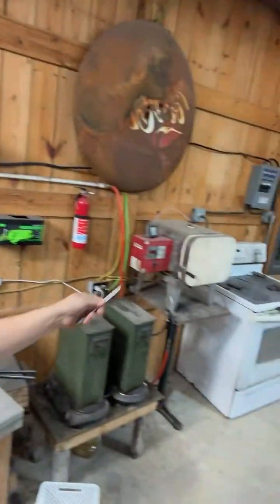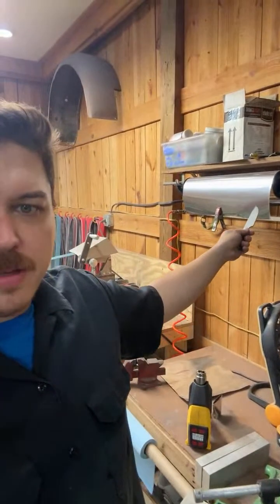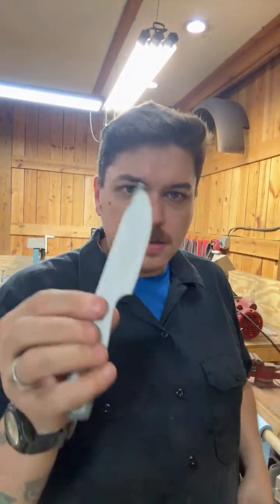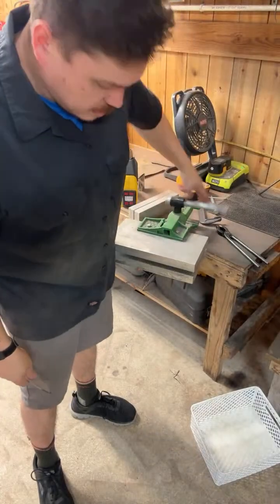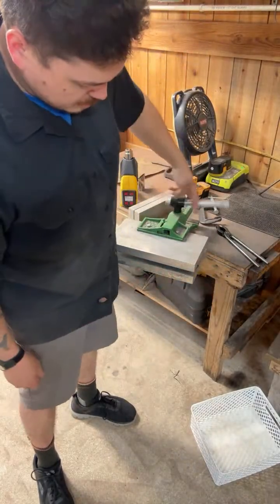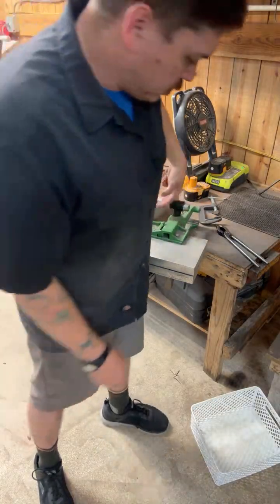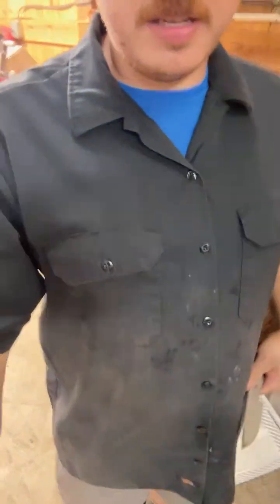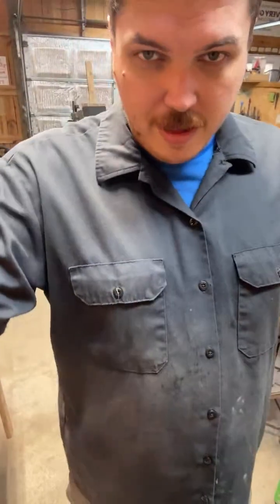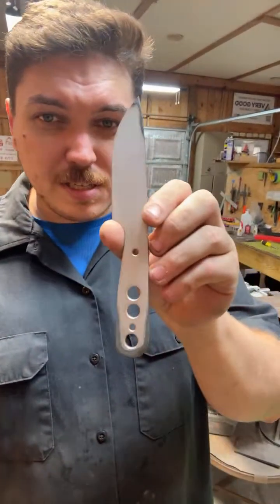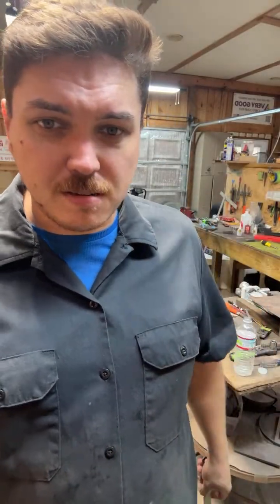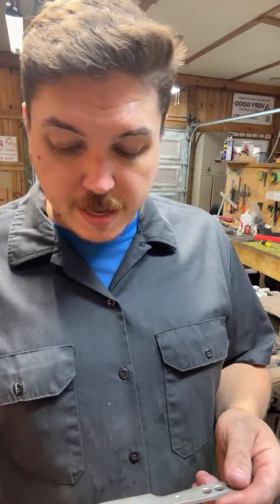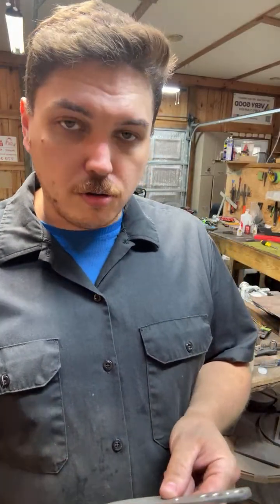I quench these. They come out of this kiln right here, wrapped in this tool wrap. This is a 309 stainless tool wrap. Okay, these blades will be wrapped in that, nice and tight so no air gets in. Okay, and then I'll put them right into here, into these aluminum plates, in the foil and all, and then I'll clamp it down tight, and that will quench them. Take them from about 1960 degrees down to what we want, which is below 1500 within 3 minutes. Honestly, these guys are about hand cold in 2.5 minutes or less and ready to go in the cryo. The faster the better, but you don't want an immediate quench, it needs to be a controlled quench. That's why we use an aluminum plate.